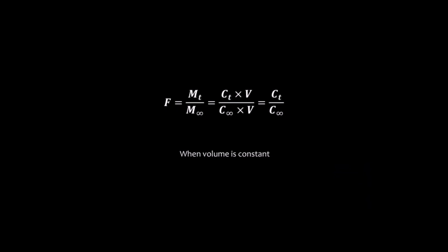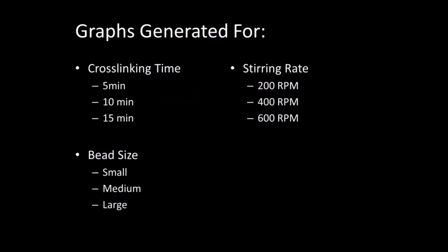In order to determine F, the concentration at time t was divided by the concentration at infinity, which is calculated based on total diffusion of the introduced tartrazine. Typically, F is calculated by dividing the mass of drug released at time t by that released at time equals infinity, but concentrations can be used here because volume remains constant. Only the first 60% of the data was used because the model is only valid for these data points.